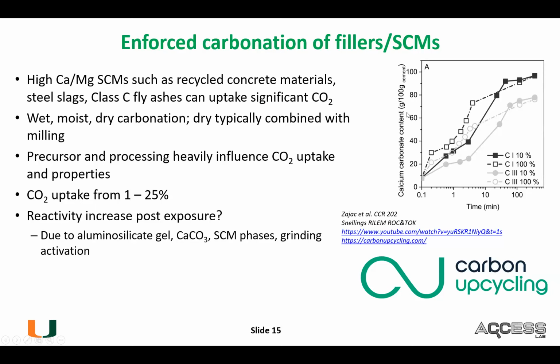The key there to having a high CO2 uptake is to have high calcium and magnesium. But of course, it needs to be in a form that will actually react, because if you just take calcium carbonate and expose it to CO2 without doing anything else, absolutely nothing will happen. But if you take these high calcium and magnesium materials, if the calcium is in, as an example, calcium oxide or calcium hydroxide or calcium silicate hydrate gel, they will carbonate.